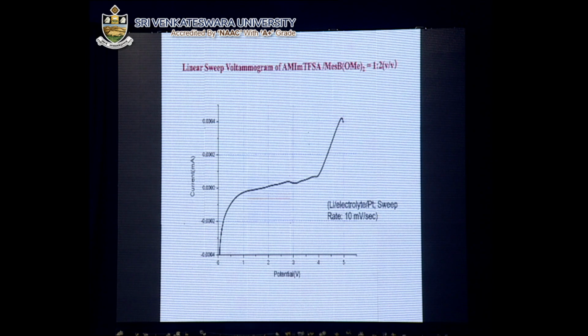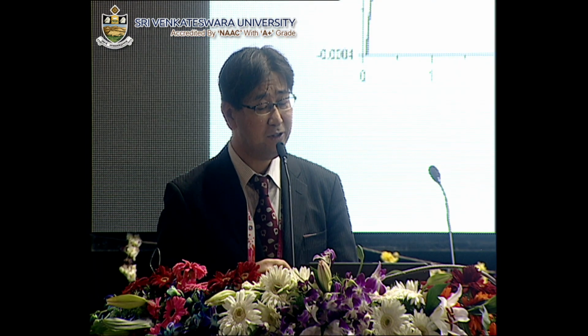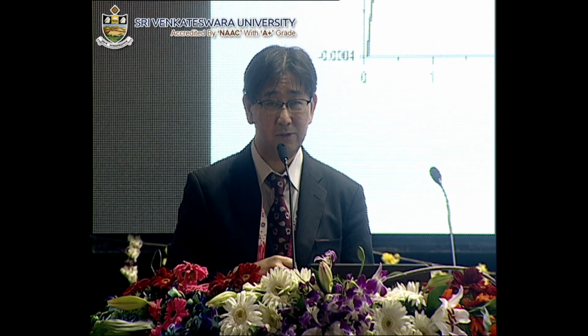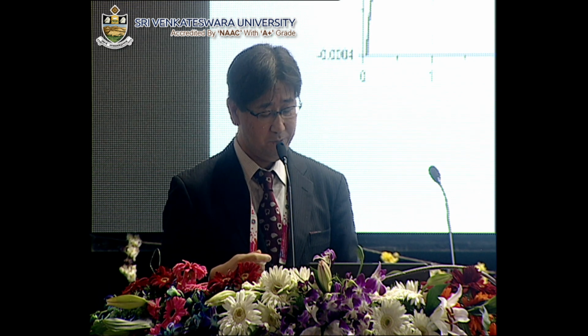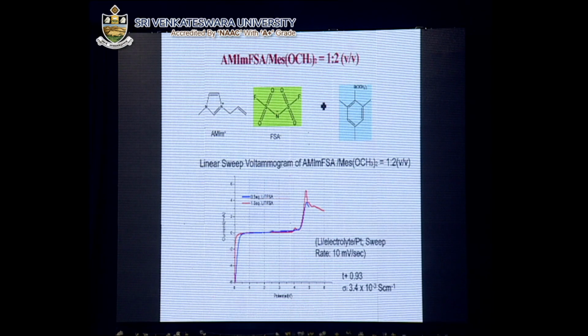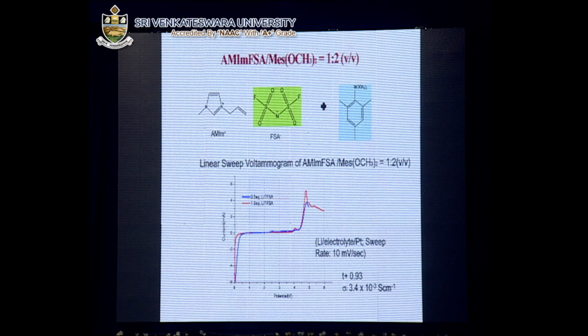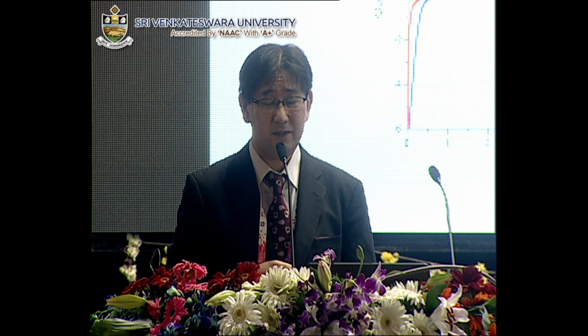And to investigate the electrochemical stability of this electrolyte, we measured the linear sweep voltammogram and found it to show approximately 4 volts of potential window, indicating its suitability for use with commercial combinations of electrode materials. And very recently, we also found that FSA type ionic liquid was also miscible with mesityl dimethoxyborane. In this case, in addition to an even wider potential window, the lithium transference number was found to exceed 0.9. And the ionic conductivity also exceeded 10 to the minus 3 Siemens per centimeter.